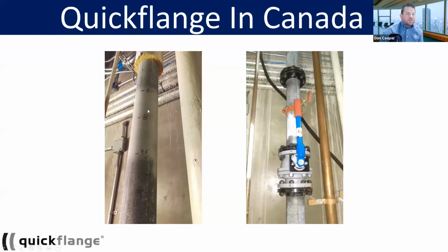We went into this job on a night shift with 2 technicians. We performed a freeze plug on the top and bottom of the tie point location. After the freeze plugs were established with liquid nitrogen, we were able to cold cut out the initial spool, and then we fitted the first 2 quick flanges on either end of the open-ended pipe. We then took the pipe that we had cut out, and we fabricated a new pup piece spool with 2 more quick flanges, and we installed the valve, installed the spool, bolted up the connections, did the hydro test on all 4 of the quick flange connections, and finished that tie point in a 12-hour shift with 2 people in a closet on a live hospital ward. No hot work required. The entire activity was cold.